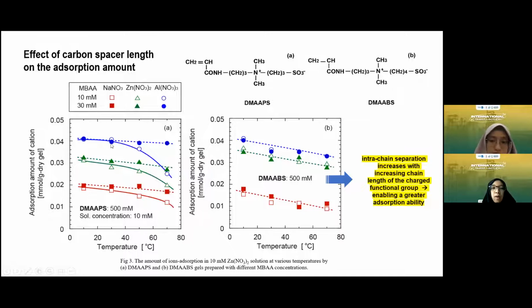30 millimolar. However, if we reduce the crosslinker concentration to 10 millimolar, the absorption amount of cation decreases gradually with increasing temperature. When we compare the DMAAPS on the left side with the DMAABS on the right side, we can see that a little bit more absorption amount can be achieved by DMAABS. This can be explained because the intra-chain separation increases with increasing chain length of the charged functional groups, resulting in a greater absorption ability.